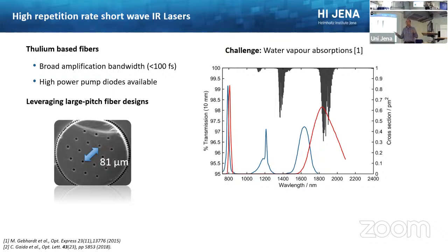thulium is quite complicated. There are a lot of different energy levels, and depending on the composition of your active material, it's possible that you can get 2 photons out at 2 micron for 1 photon at your pump wavelength. They have certain cross-relaxation processes. And if you go to this regime, you can get to quite high slope efficiencies of, let's say, 70%